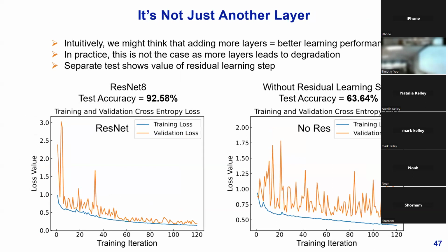And so I just want to add in this little tidbit here. In terms of supervised machine learning work, it's not necessarily all about just making your model more complicated or just adding more layers. There was a thought process, even though it was a little wishy-washy somewhere in the middle there, a genuine motivation for why we picked the things that we did. And so we can see that by taking the exact same neural network architecture of ResNet 8, but just removing that residual learning step, just simply taking out the adding step that happened at the end of those learning blocks, the performance is greatly reduced as a result. And so the big takeaway here is that this residual learning step, even though it seems small in the grand scheme of things, was actually playing a significant role in improving our phase recognition performance from these one-shot patterns.